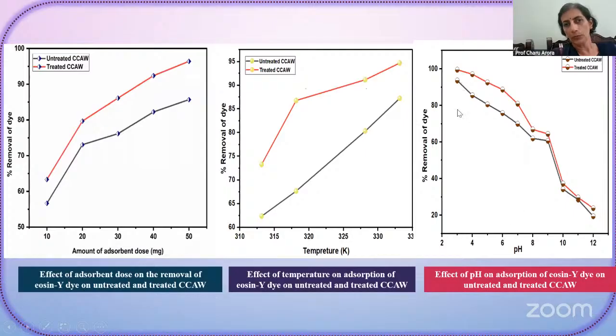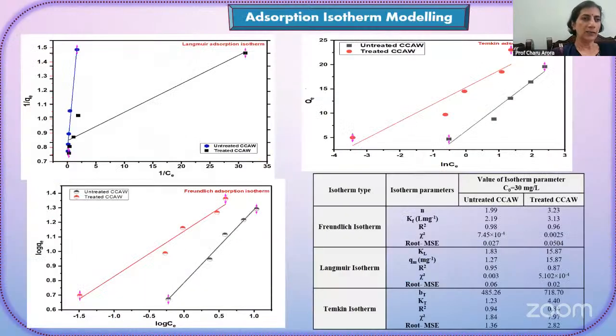Here it was observed that at pH 3, lower pH meaning acidic medium, is favorable. It favored the removal of dye. These are the adsorption isotherms plotted: Temkin, Langmuir, and Freundlich. And you can see that the highest value of R square is for the Freundlich adsorption isotherm.